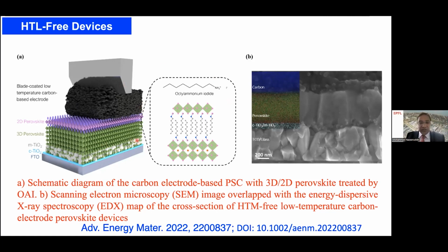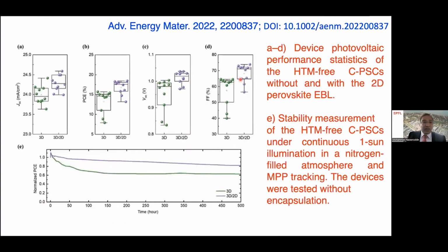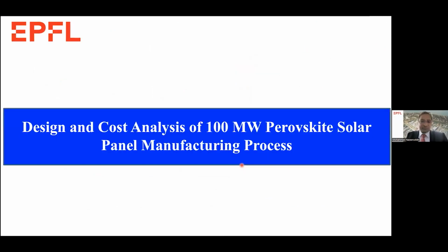Using this configuration, the two-dimensional perovskite structure is shown here. Here the cation is not phenylethylamine; it's an octylammonium iodide cation we have selected. Using this configuration, the efficiency reached over 18%, and the stabilities are quite high. But the remarkable thing here is that this is a hole transporting material free device giving very high efficiencies. In our previous publication we have shown that the stability of these carbon-based perovskite solar cells remains for 10,000 hours. So these are highly stable, reasonably performing solar cells.